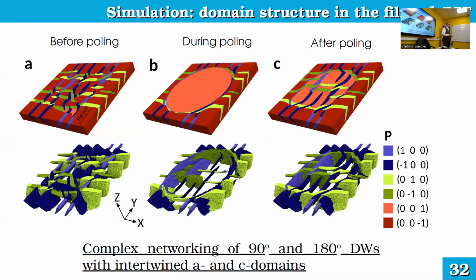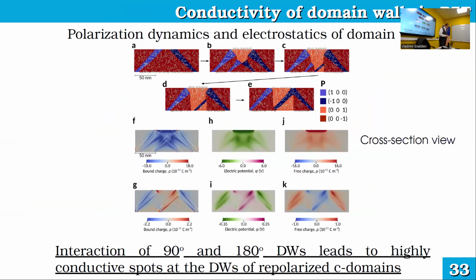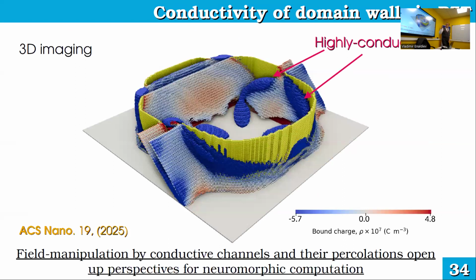So we modeled also this case to know why this conductivity happens, and found out that actually in these PZT thin films forms a very complex network structure of interconnected domains. And because of elasticity compatibility conditions, because of large deformations of this film, all domain walls, including 180 domain walls, are inclined and they're all charged, and they attract free charge carriers. These bound charge walls attract free charge carriers from the volume of the material. So basically, we modeled the full three-dimensional case, which shows that high conductivity traces follow the places where different types of domain walls are interconnected.